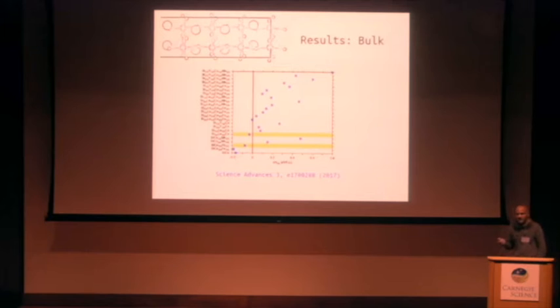multiferroic phase transitions. So we started wondering how we could bring this back, since this happens at high pressure, but of course for practical purposes we would like to have this at ambient pressure, right? So we started looking at two different possibilities. One was solid solutions, by doping, right? Essentially we started doing some DFT calculations, monitoring the enthalpy difference at zero pressure, between the P4MM